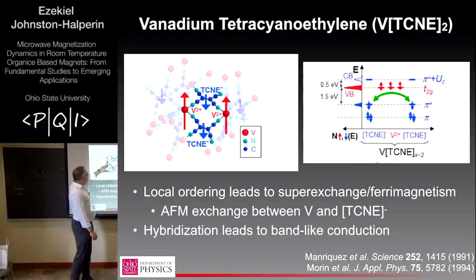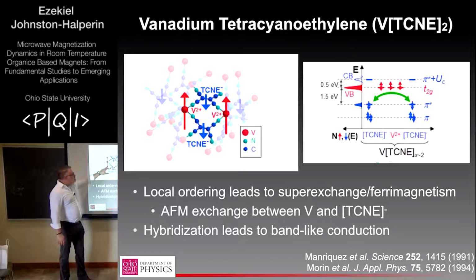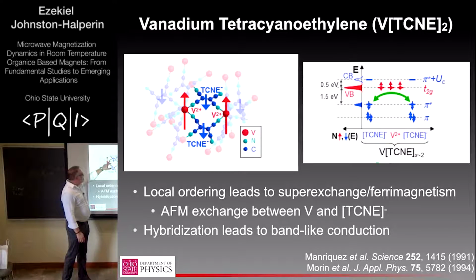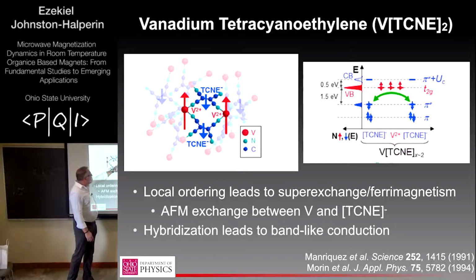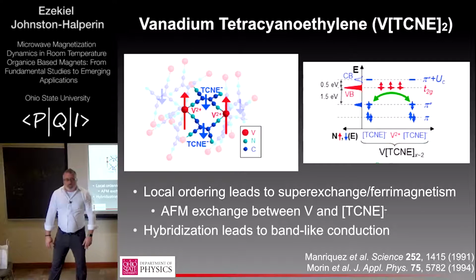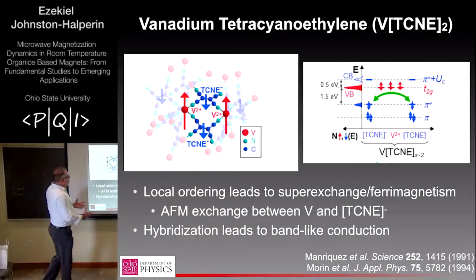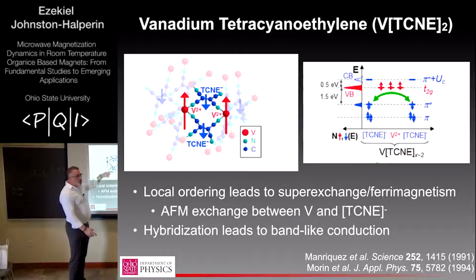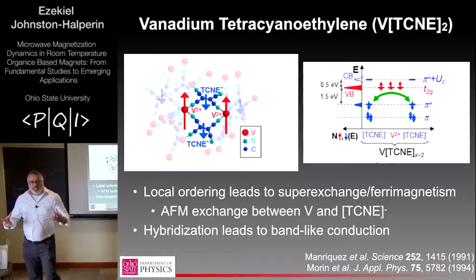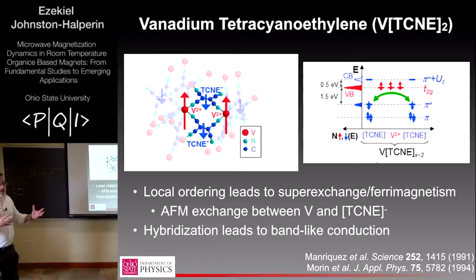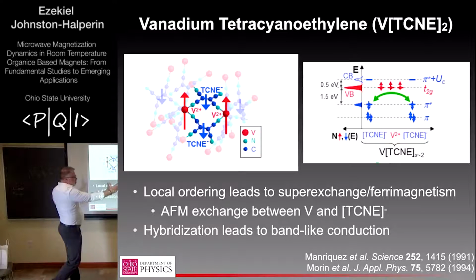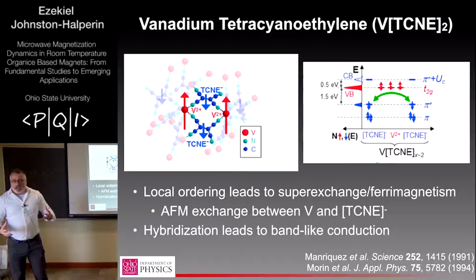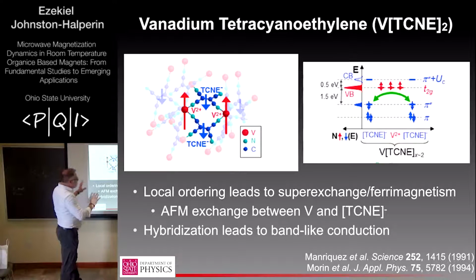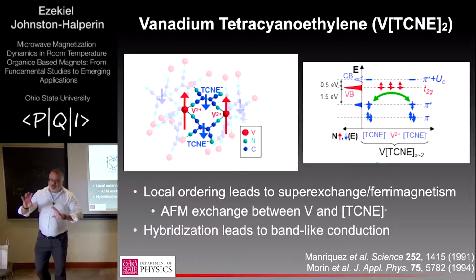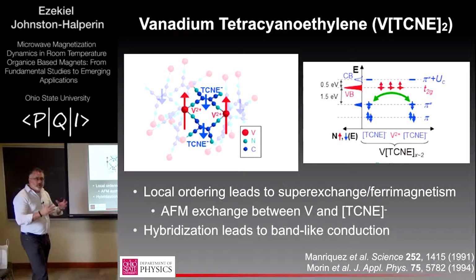It's coordinated through these vanadium. Every vanadium connects to six different nitrogen groups. And then vanadium can talk to vanadium through the molecular orbitals of this TCNE. Through various structural characterization techniques, this local ordering around the vanadium is very well defined. So it's not amorphous, it's not random. But long-range structural order is harder to identify. I'll come back to that later in the talk, but for now, we can think of it as somewhere between amorphous and polycrystalline with very small grain size.